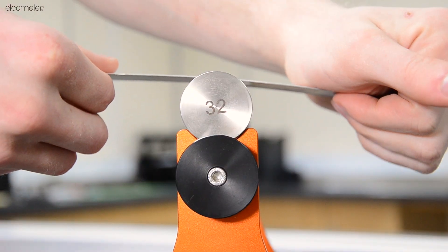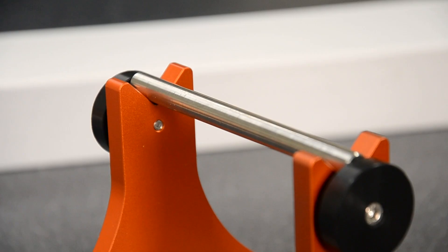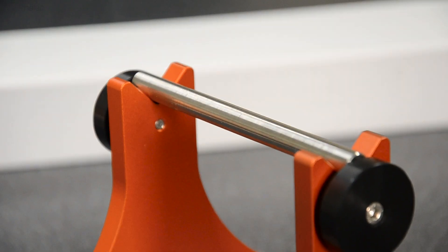The coating on the metal sheet should then be inspected after every bend. This will allow you to determine a more precise point of failure for your coating by evaluating flaws such as cracks, discoloration, gloss change and adhesion of the coating to the panel.